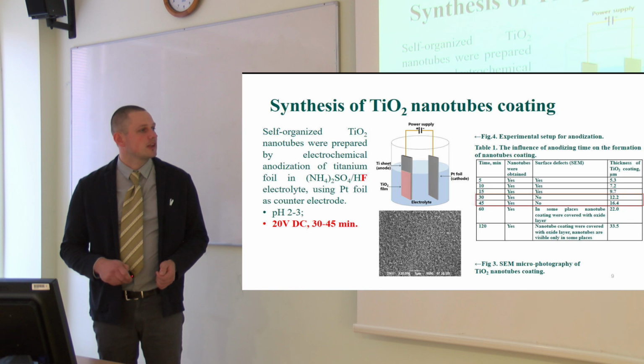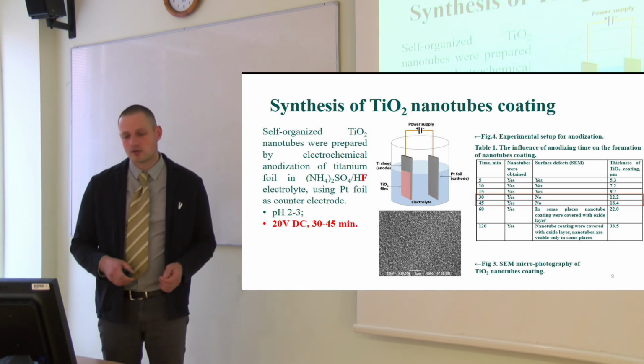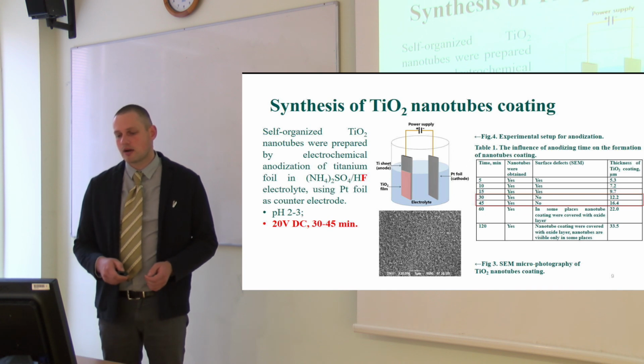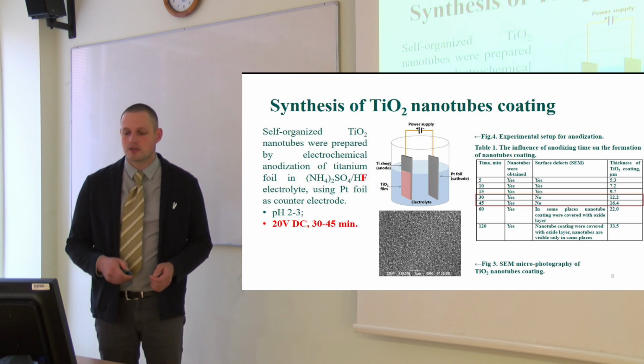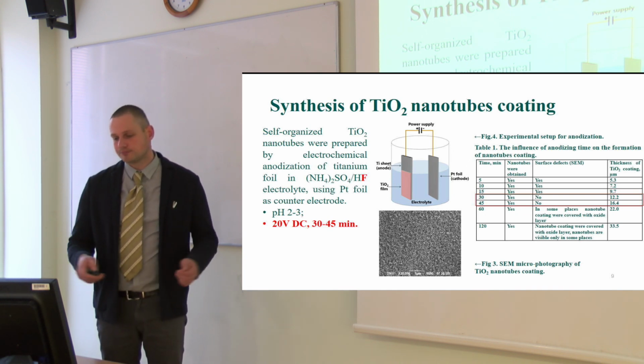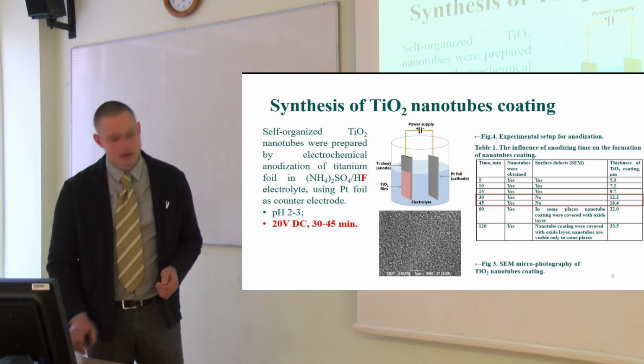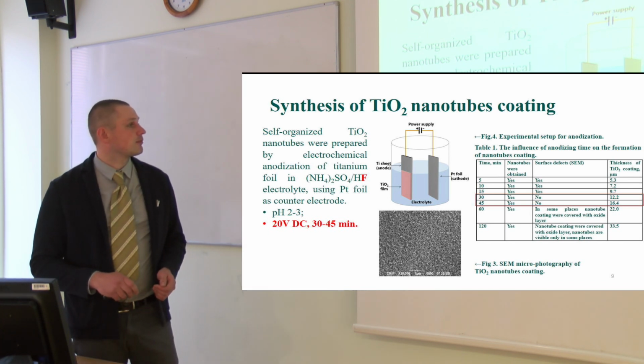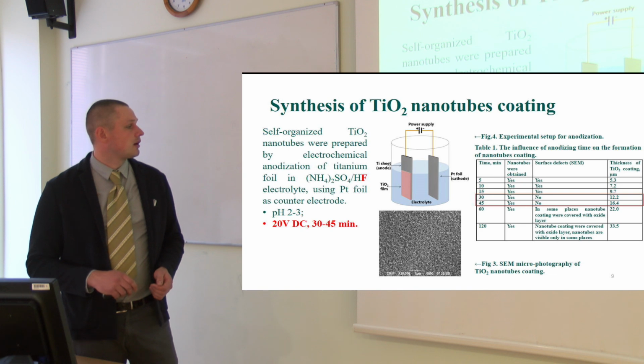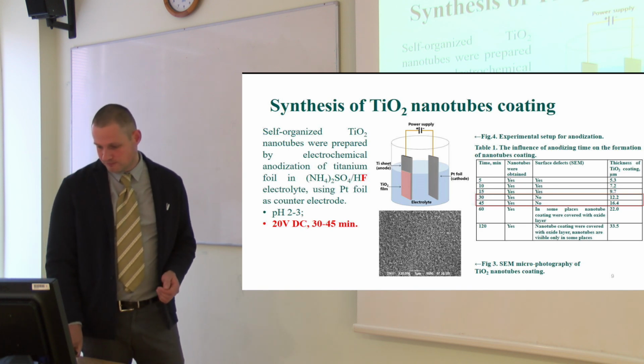We have tested various experimental durations. The best results were with 30 to 45 minute experiments. The power was DC, 20 volts.